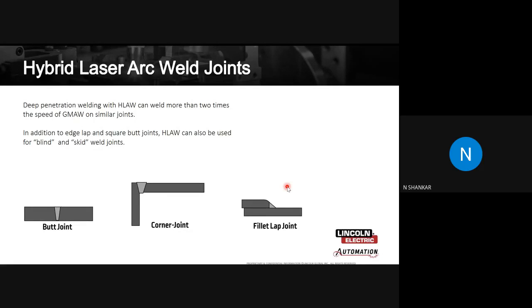You can weld at more than 2 times the speed of GMAW, which means even with a very good GMAW process, you're looking at welding at 1.5 to 1.6 meters per minute. You can travel twice the speed with the hybrid laser arc welding machine. You can also do 100% penetration on square butt welds. It can also be used for blind and skid welds, actually. So it finds wide, extensive application.